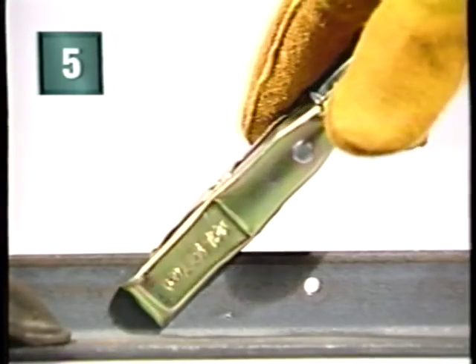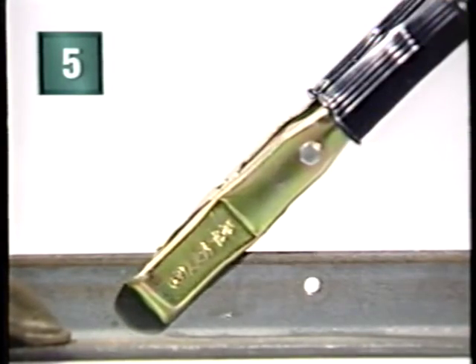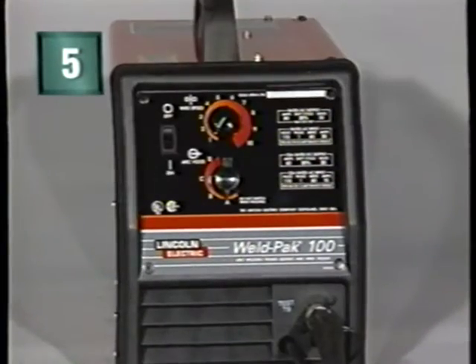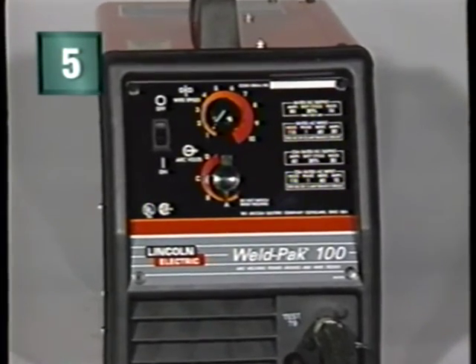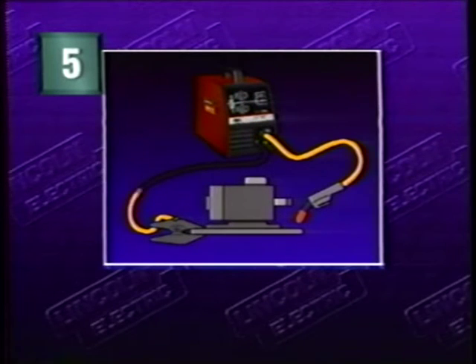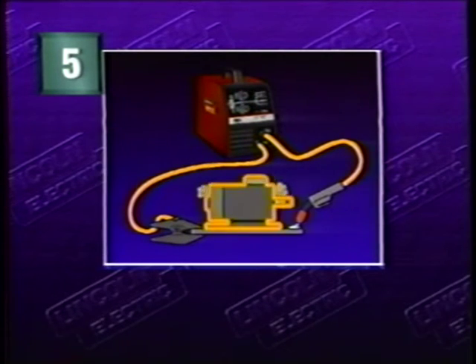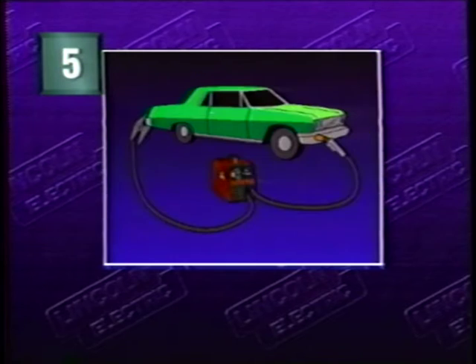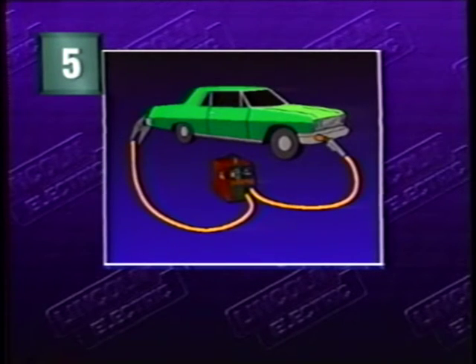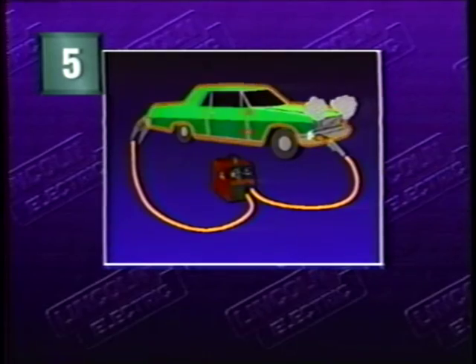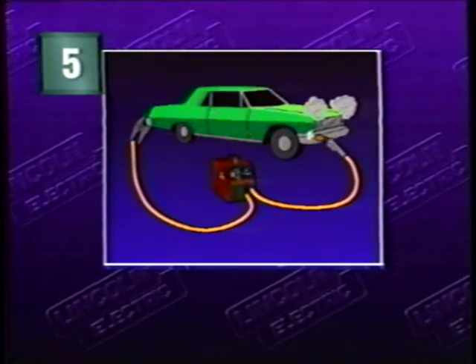Once you've adjusted the settings, attach the work clamp as close to the joint as you can. Be sure it makes good electrical contact. This will reduce the resistance in the welding circuit and let your weld pack unit perform efficiently. And you'll avoid extending the circuit and accidentally damaging other parts. Also, use care in preventing the electrical circuit from going through hinges, chain hoists, or electrical components. It can severely damage them.